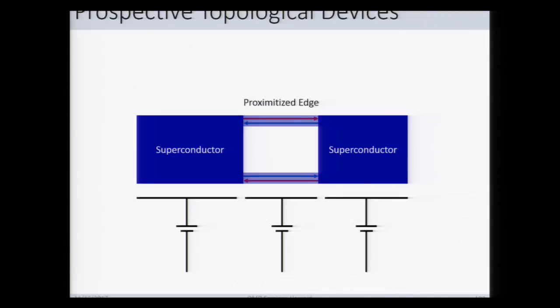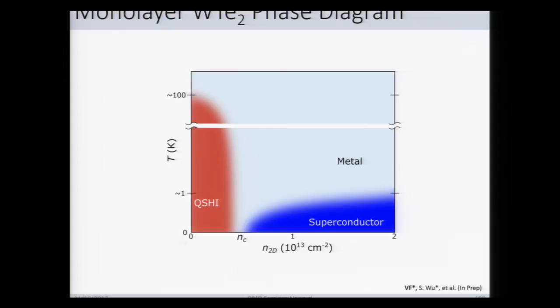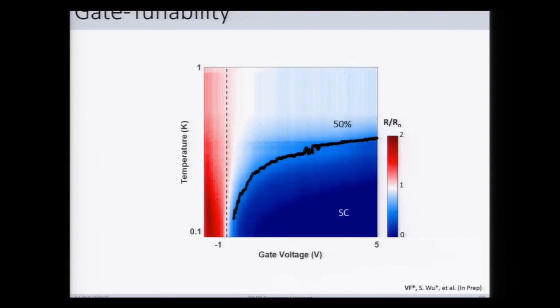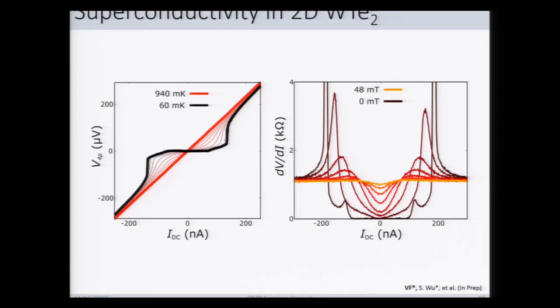From the phase diagram that you showed, it seems like you should go from superconductor to metallic region to the spin Hall phase. Yeah, so we can't necessarily confirm in this narrow region here whether it's a sharp transition from superconductor to insulator or if there's something intermediate there. I mean, we're not necessarily at low enough temperature. And we have this complication.